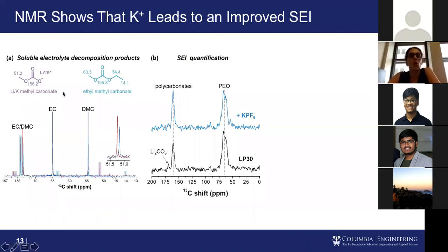How is the electrolyte decomposition different in these two solutions? So we take a look at the solution NMR after extended cycling in the battery. And what we see is that when we have KPF6 present in our electrolyte, we actually have much smaller amounts of these soluble electrolyte decomposition products. So these short chain alkyl carbonates are not as present in the electrolyte. And when we have KPF6, we also have a different ratio of these polycarbonates and polyethylene oxide polymers in the solid phase that's attached to the lithium metal surface, that is probably changing the ionic conductivity to the lithium metal electrode. We also don't see any of this lithium carbonate material, and lithium carbonate is known to be a poor ion conductor. So in a way, it sort of blocks lithium ion transport to the lithium metal surface.